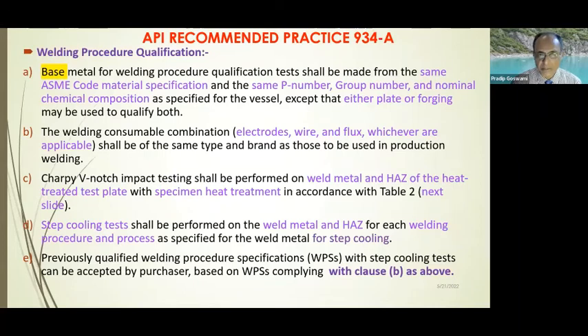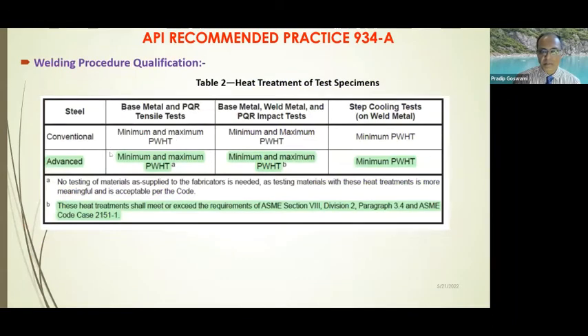And as I explained in the previous slides, the difference or shift in the impact values after the step cooling test should not be more than 10 degrees C. And we can see here the typical heat treatment requirements for the advanced steels. For the PQ qualification, we have the minimum and maximum post-weld heat treatment. Both have to be applied, meaning the coupon plate has to undergo the minimum and the maximum. The minimum is what is intended for the vessel as per ASME Section 8, that is going to be adopted in practice following the fabrication. And the maximum is something like an empirical estimation. Assume that you have to do a couple of repairs, and in that way, how much is the maximum allowed?